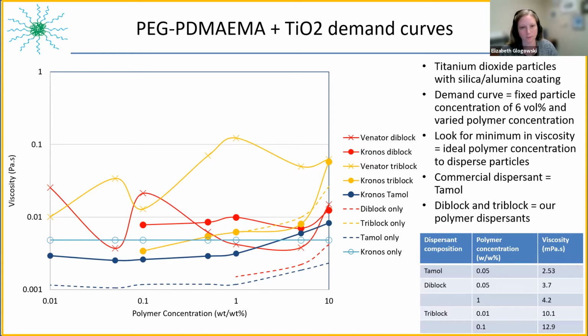Then if we have an effective dispersant, we will see a dip, a minimum in the viscosity. And then when the polymer behavior takes over, as we increase the polymer concentration, we expect to see an increase in the viscosity again. So the ideal polymer concentration for a dispersant is that minimum in the viscosity.